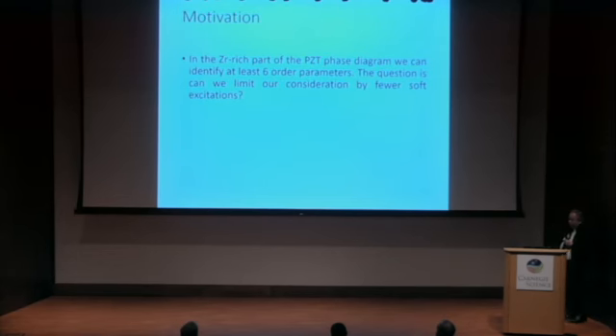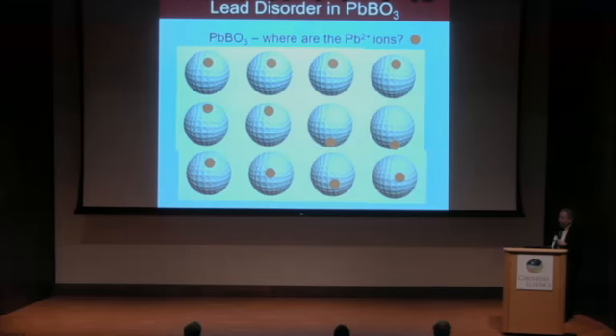So what's the motivation? If we analyze the structure or the phase diagram of lead zirconate titanate, on the left-hand side, let's say at the zirconium-rich part, we can identify, let's say, 6 order parameters. I should say we can identify 5 different types of superstructure peaks, and we do know that there is a softening of the mode at the zone center. So finally, it's ferroelectric. So the question is if we can find some general origin or general description for this.